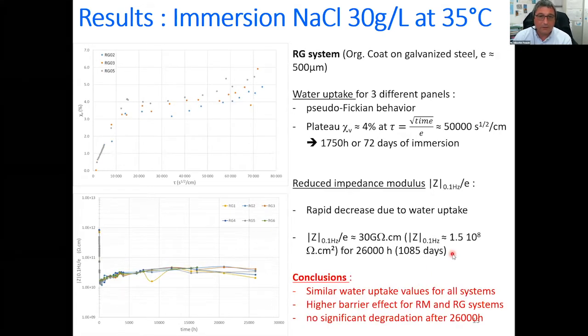Now the results for the RG system. So remember, this is organic coatings that were applied on galvanized steel. We've got the same water uptake value, rapid water uptake, and then a plateau about 4% and a slight increase. And for the reduced impedance modulus, we've got the rapid decrease and a quite constant value for more than 1,000 days of immersion.